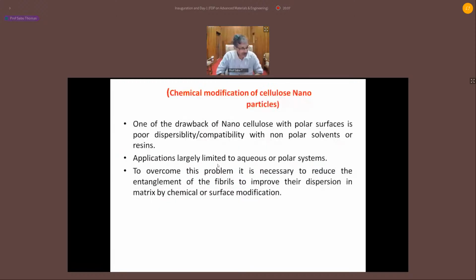Now I wanted to show you one of the drawbacks of nanocellulose: its polar surface, and its dispersion in non-polar polymers is very poor. Look at, I got a new project with Apollo Tyres. They wanted to incorporate nanocellulose into tire tread and tire sidewall. Particularly, we focus first on tire tread. When you mix nanocellulose with SBR rubber or natural rubber, there is a big question of incompatibility.